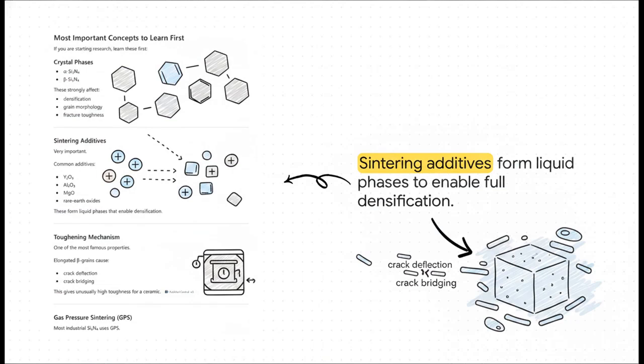Let's zoom in on those additives for a second, because honestly, they are absolute game changers. Silicon nitride all by itself is notoriously stubborn to densify, but by adding sintering aids, things like yttrium oxide, aluminum oxide, magnesium oxide, or even various rare earth oxides, we fundamentally change the game. These additives form liquid phases at super high temperatures. It's this liquid phase that basically pulls the particles together, enabling full densification. Without them, you'd just be left with a porous, weak block of material.